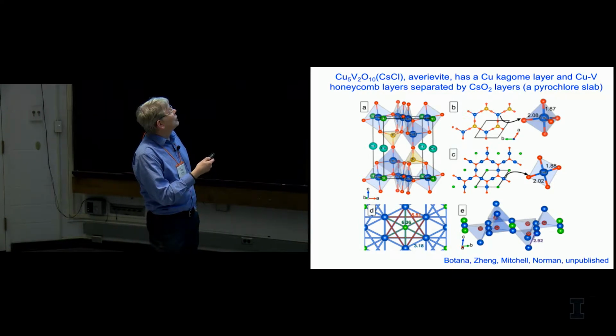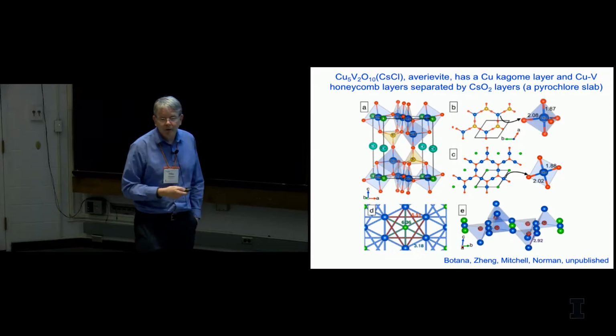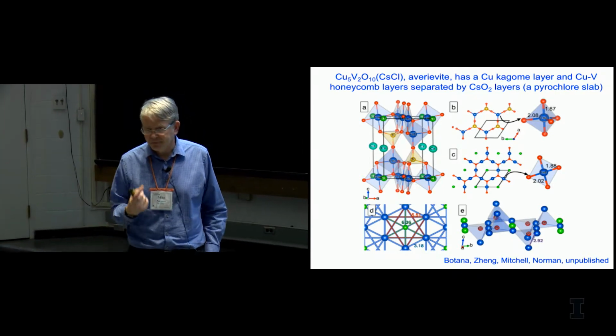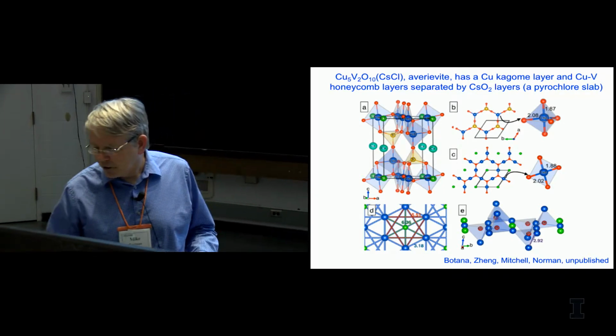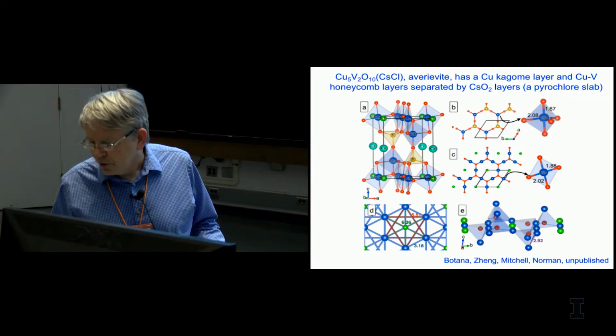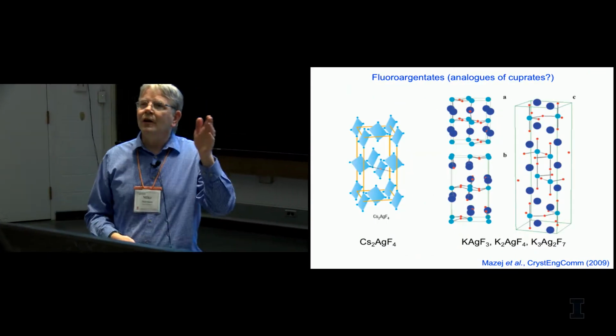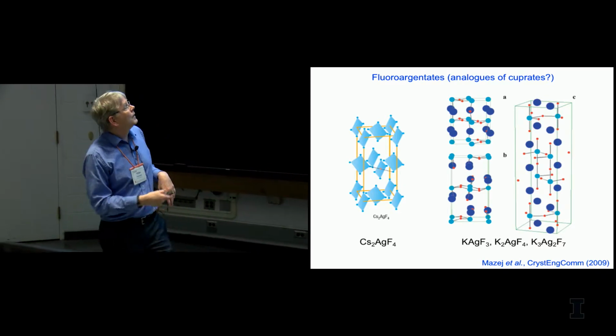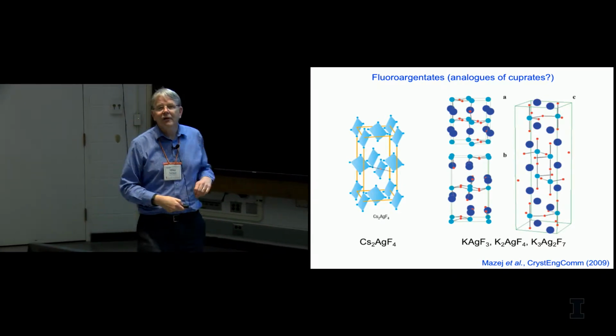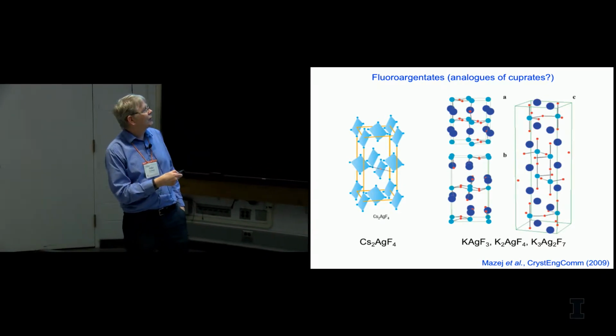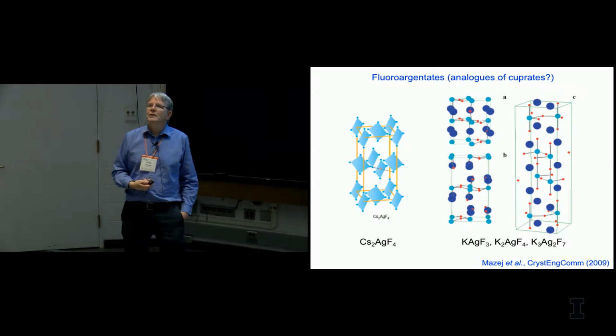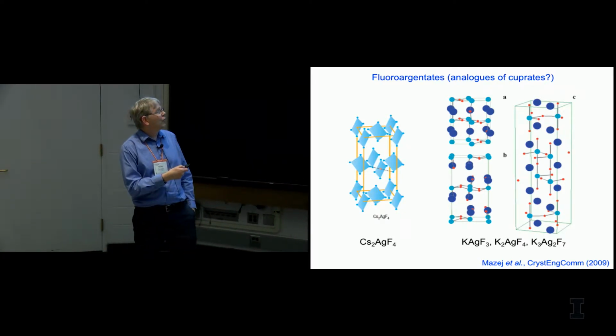But doping studies where you would actually, say, replace vanadium by titanium, where you could dope carriers into this material, have not been done yet. So some people have speculated maybe we can go to other things besides copper. If you're thinking copper, the next thing down is silver. And it turns out that silver oxide doesn't work for various reasons, but if you had silver fluoride, it would work. It turns out that the relation between silver d and fluorine p levels is about like in copper d and oxygen p.